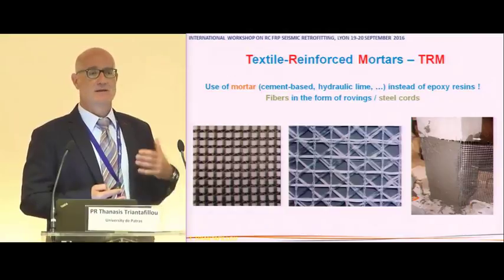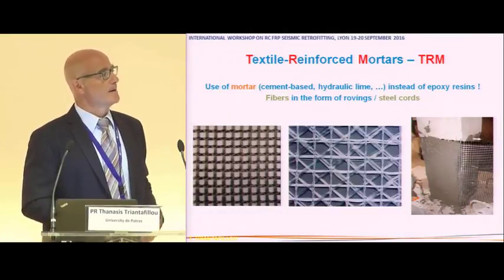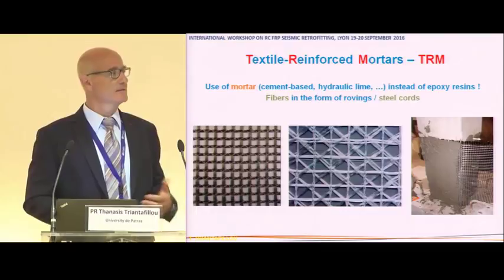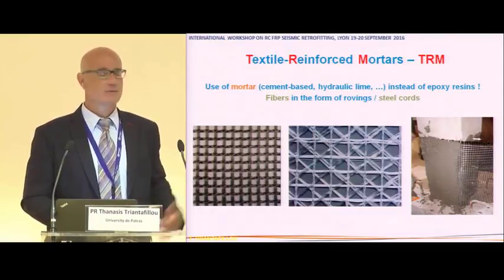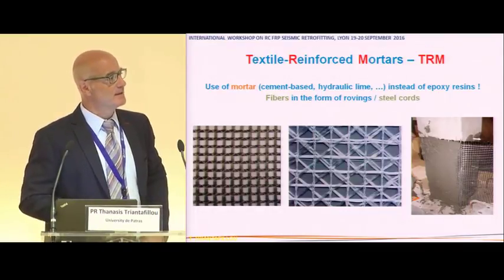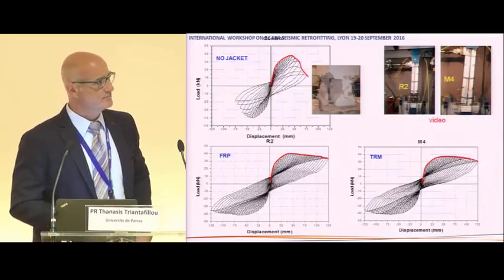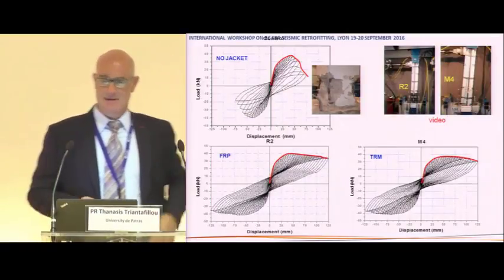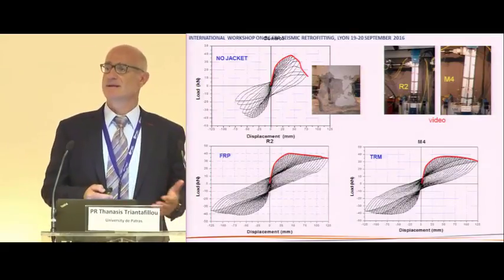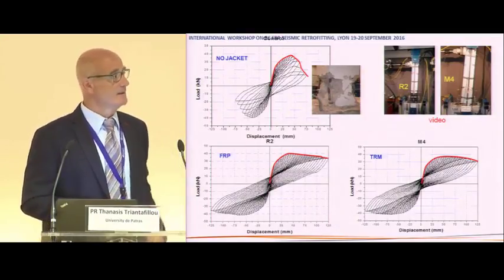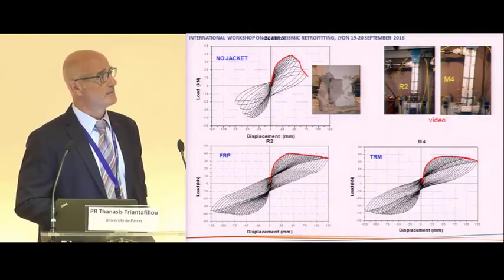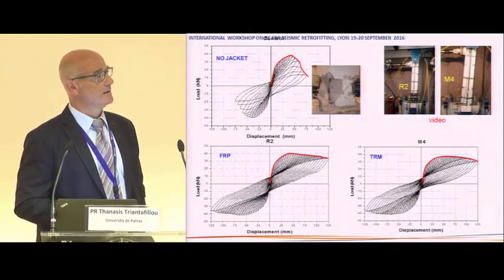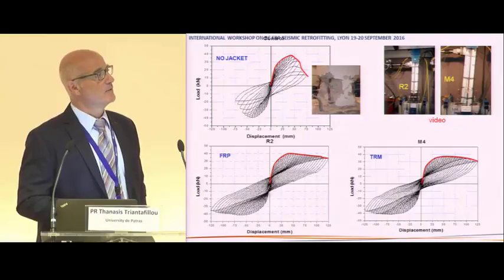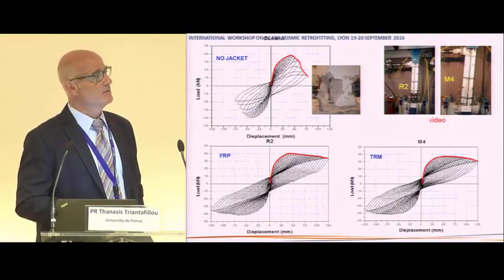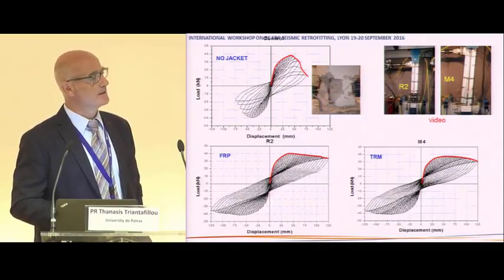So those are basically composites where the matrix is a non-polymeric one, it is an inorganic one, and the fibers are typically in the form of a textile. This system is quite effective. It is nearly as effective as FRPs. And here is the proof. If you, for example, confine locally a reinforced concrete column with an FRP system, with an FRP jacket, and then you do the same with a TRM jacket, with a textile-based jacket, and you compare the response of the two